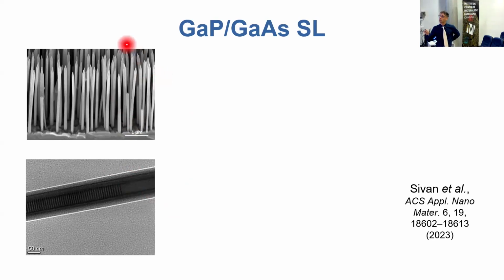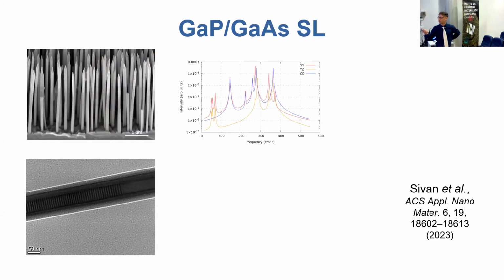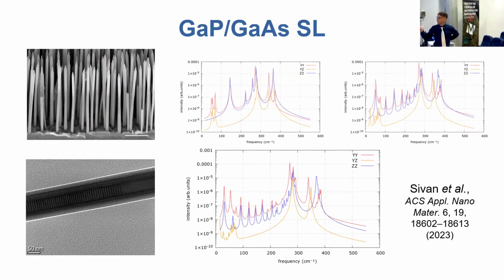So we computed the Raman spectra of this superlattice for the 5 periods I mentioned before, and you can appreciate here the results for the shortest, mid, and longest period we have simulated. The situation is particularly interesting. You can see that in every plot, the 2 optical frequencies of both gallium phosphide and gallium arsenide are clearly present and shape the overall structure of the Raman spectra.